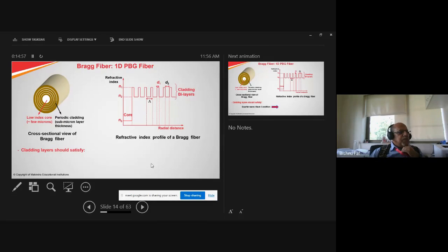Now, if you study propagation in this, you can show that light will be confined in the core. In general, from electromagnetic theory, in the central core region we have a smaller refractive index, surrounded by higher refractive index, eventually again falling into air. So it's a leaky structure. So light, even if you launch into the center, should immediately leak away into the surrounding media.